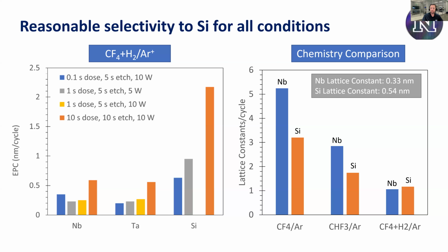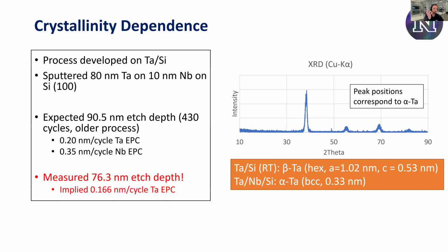So cool. I mentioned before we were interested in crystallinity dependence. We were making our first devices, and these first devices actually under test just got cooled down in a dilution fridge over the weekend. So we should be getting results soon on real resonators. But we took the same process. When we did our process development, everything was just 80 nanometers of tantalum sputtered, and all our processes were just on silicon. That actually gives you the beta phase, which is a little bit different from the alpha phase of tantalum. When you have a seed layer of niobium, you get more of an alpha phase, a different crystallinity of tantalum.